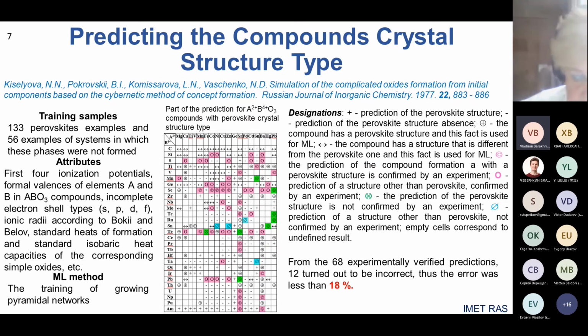Much more often in machine learning, problems of compound crystal structure type prediction are solved. An example of such a solved problem is the ABO3 composition perovskite prediction, which we carried out in the 70s. The table shows the perovskite prediction comparison results with the new experimental data. From the 68 experimentally verified predictions, only 12 turned out to be incorrect. Thus, the errors were about 18%.